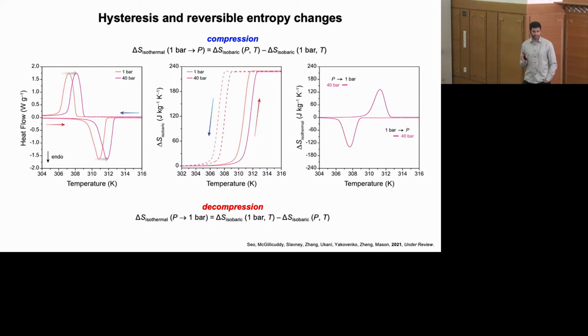And the main thing to notice here is that the forward transition, the transition that's induced by compressing from 1 bar to a higher pressure at 40 bar, does not have any overlap with the reverse transition that's induced by going from 40 bar to 1 bar. And that's because of the hysteresis associated with the phase transition. So what this means is that between 1 bar and 40 bar, you cannot drive this transition reversibly.